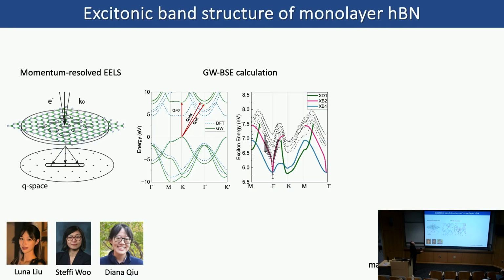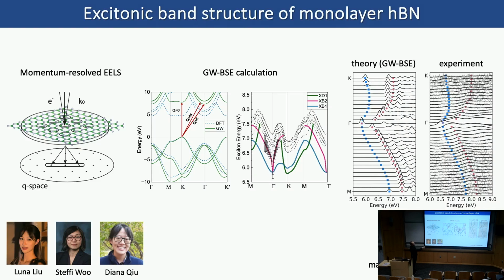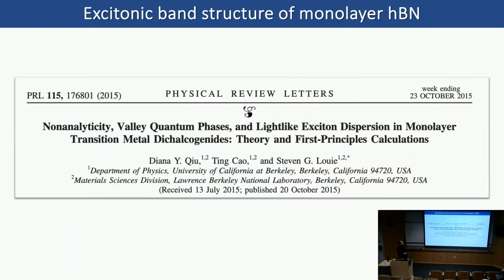Okay, and from this theoretical calculation, we can also predict what it should look like inside a momentum-resolved EELS experiment. This is theory, and this is what we got from experiment. And instantaneously you could see that there's a pretty good match when it comes to this pink band. Starting from the gamma point, it's actually low in energy, but once you go away from the gamma point, that peak shifts dramatically. So it matches quite well with the theoretical prediction, which actually confirms that this linear dispersion of the exciton actually exists. And this is not a new topic.